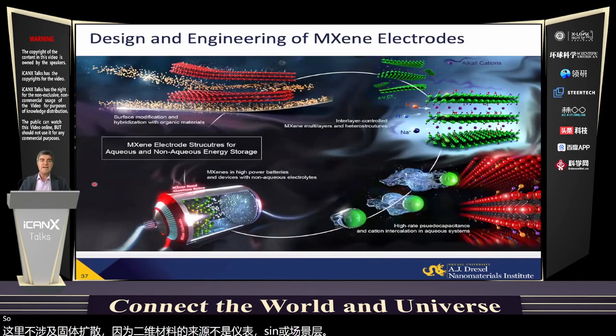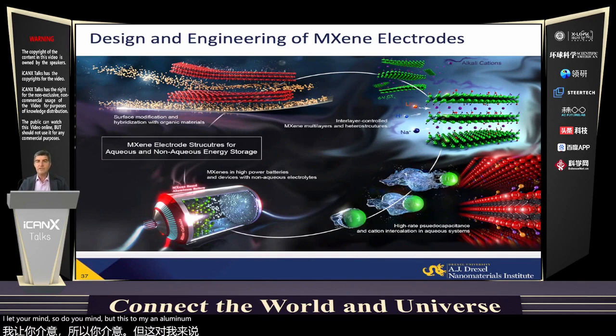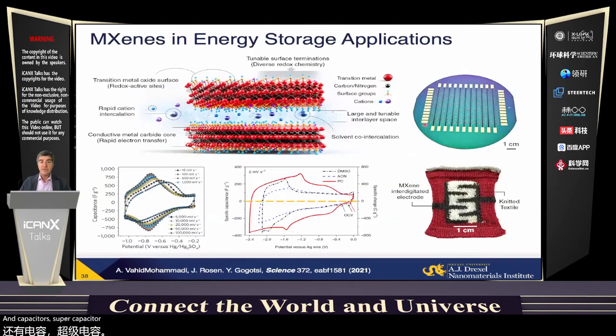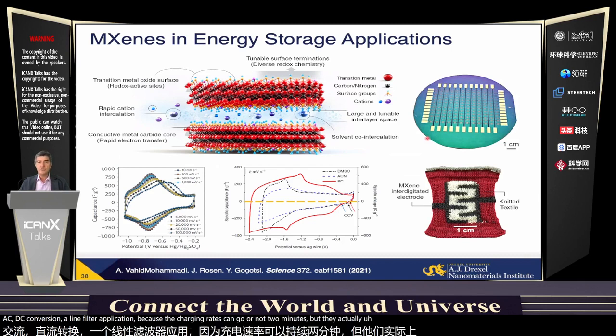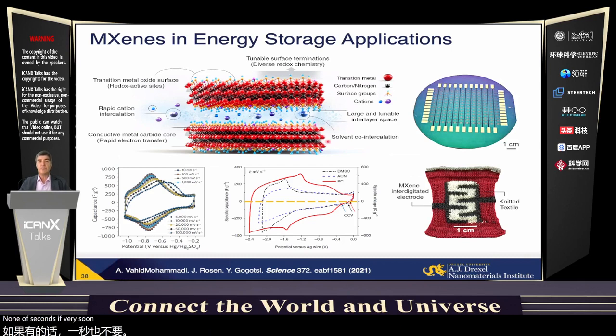So many applications emerge in energy storage, covering pretty much almost all kinds of batteries: lithium ion, sodium ion, potassium ion, aluminum ion, lithium sulfur, sodium sulfur, and capacitors, pseudocapacitors here, which actually show extremely high performance and the potential also for AC-DC conversion, line filter application, because the charging rate can go not 2 minutes, but actually to nanoseconds if very thin films of MXenes are used.